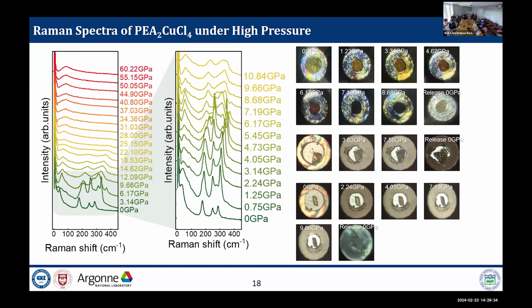Actually, the magnetic ordering in PEA2CuCl4 is the ordered state of dx square minus dy square or dy square minus dx square orbitals. So from the Jahn-Teller distortion, this means the magnetism can disappear with external pressure in PEA2CuCl4.